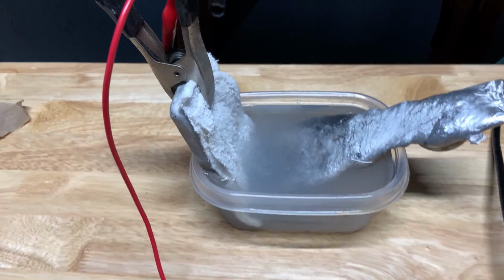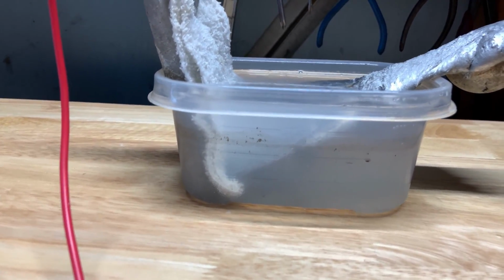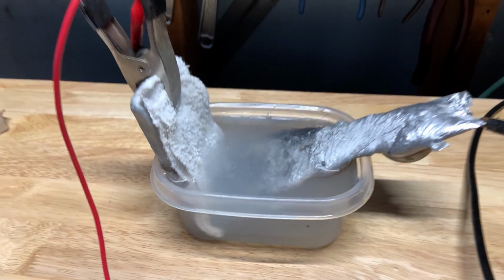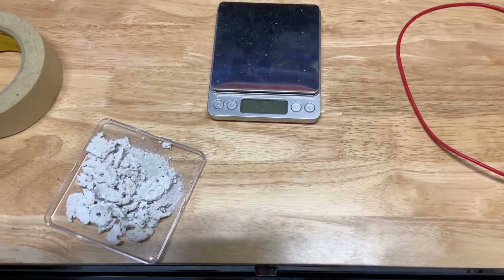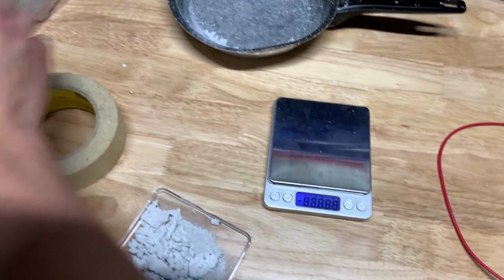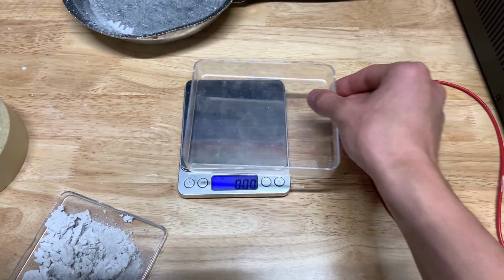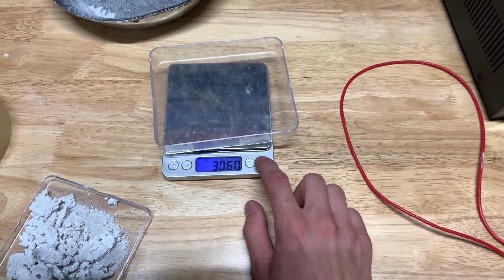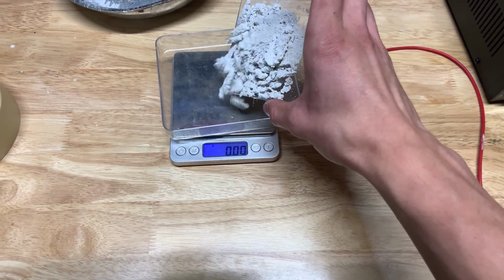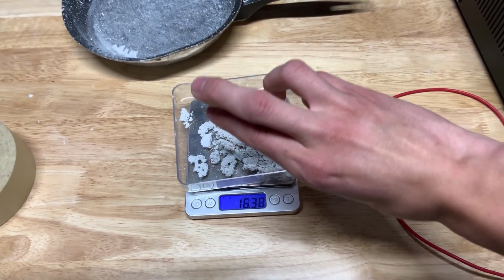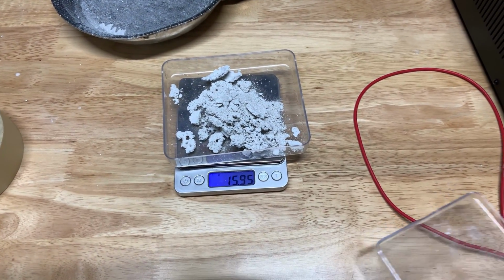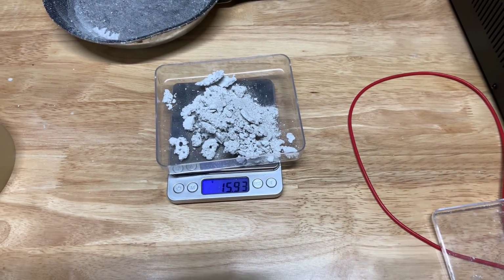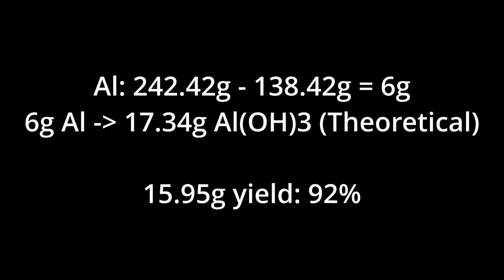I used a towel as a barrier between the 2 electrodes, that way they could get really close to each other, because without all of the electrolyte that I was using originally, the current dropped down to about 100 milliamps at 30 volts. After letting the setup run for about 2 days, I was left with about 15.95 grams of powder, which did include a bunch of losses from drying it out because I just threw it in the pan to heat it up real quick instead of waiting to dry it out in the oven, and a lot splattered everywhere. But 15.95 grams isn't too terrible for 100 milliamps at 30 volts.